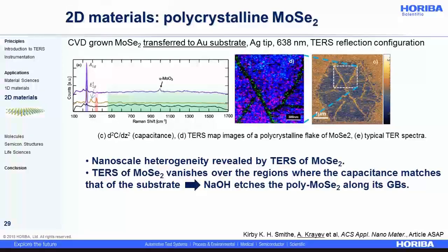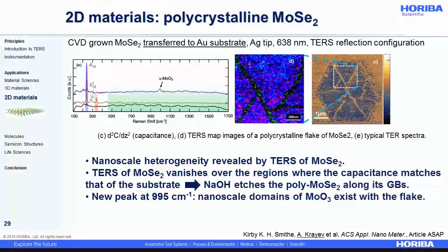Then we observed that the TERS of molybdenum diselenide completely vanishes over the regions where we see that the capacitance matches that of the substrate. So no more MoSe2 there. It confirms that the NaOH etches the polycrystalline molybdenum diselenide along its grain boundaries. And finally, in the blue spectrum, you can see a new peak, a new TERS band at 995 cm^-1, which can be attributed to molybdenum trioxide, MoO3. Then nanoscale domains of molybdenum trioxide must exist within the molybdenum diselenide flakes.